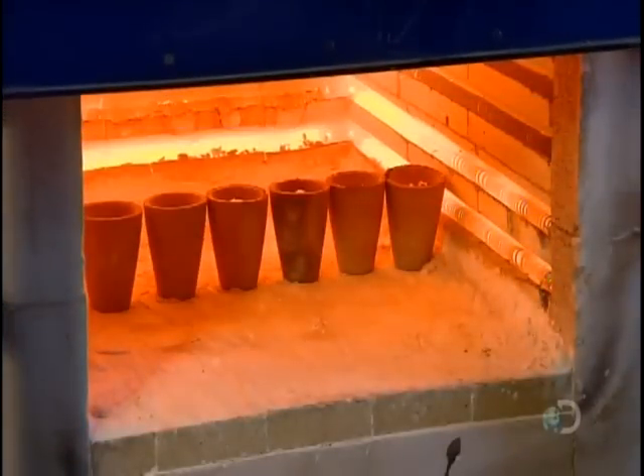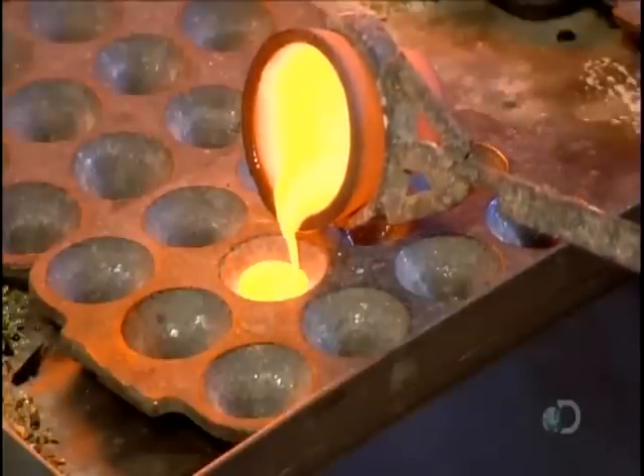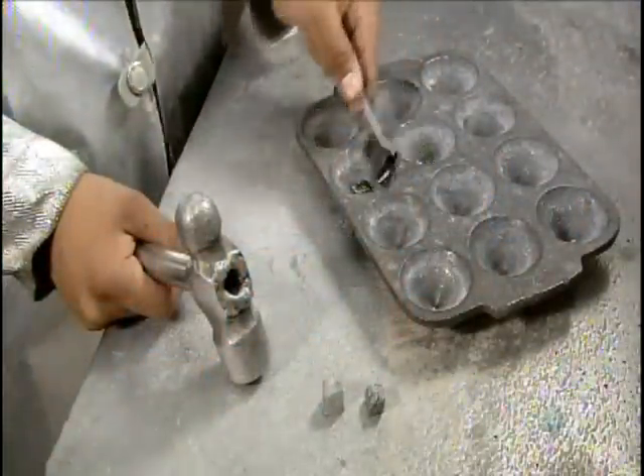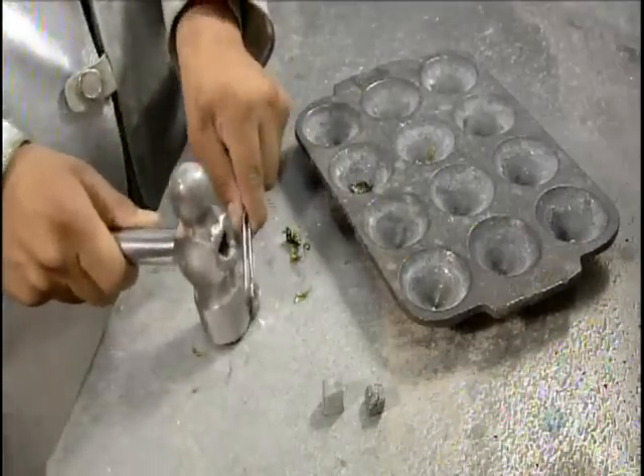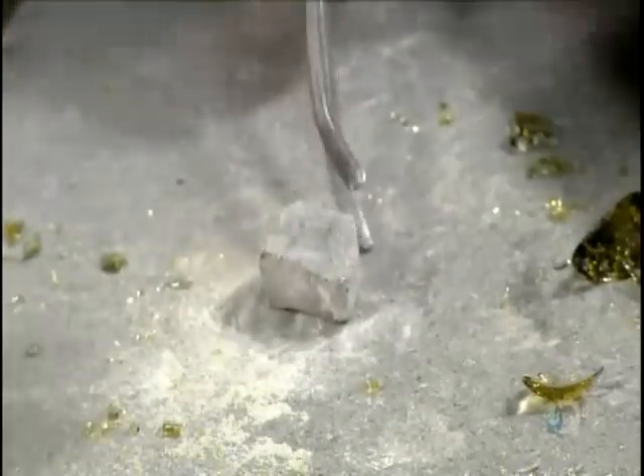In the mining company's lab, technicians continuously test ore samples to determine the grade — the term for the quantity of silver per kilogram of ore. They heat the samples to 1,093 degrees Celsius for about an hour to burn off the impurities. What's left after the burn-off are the silver and other metals, such as lead, zinc, copper, selenium, and cadmium.